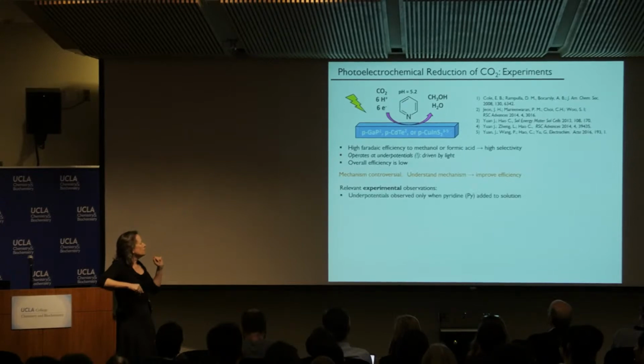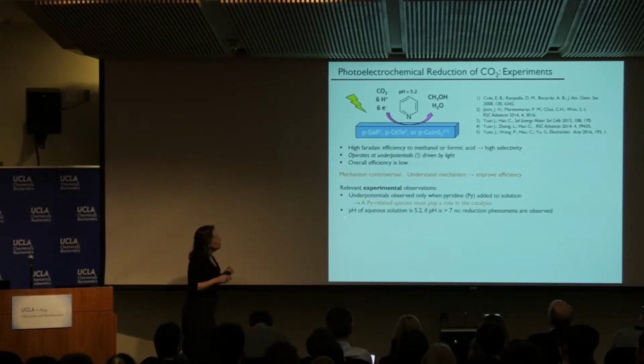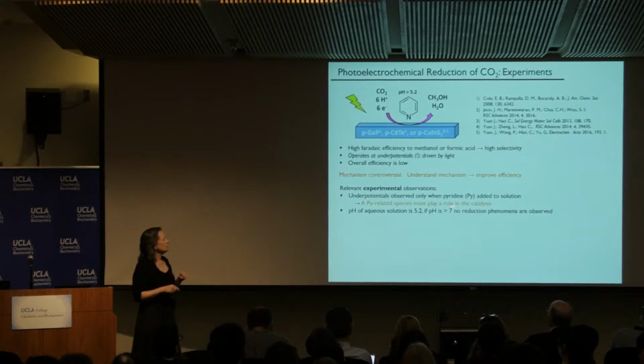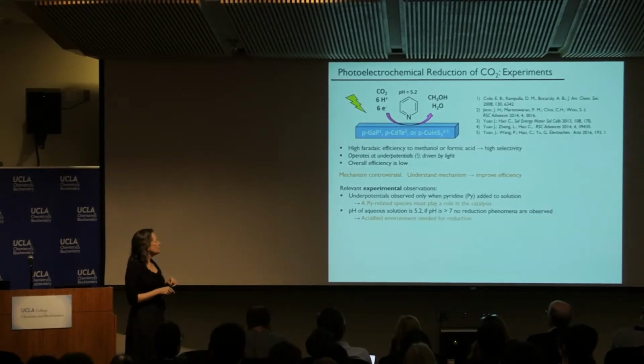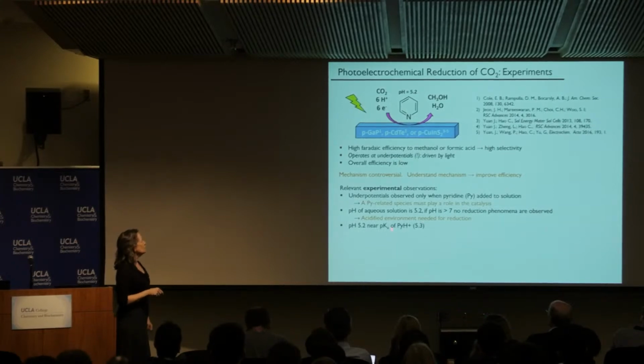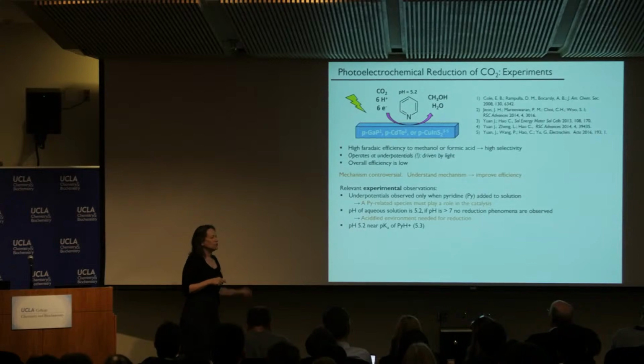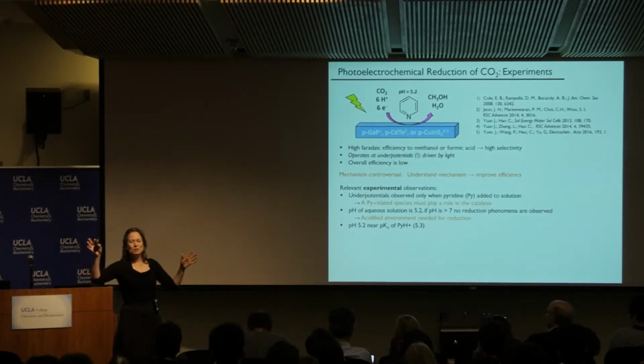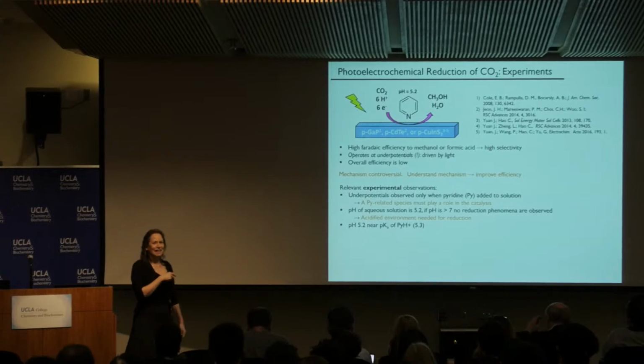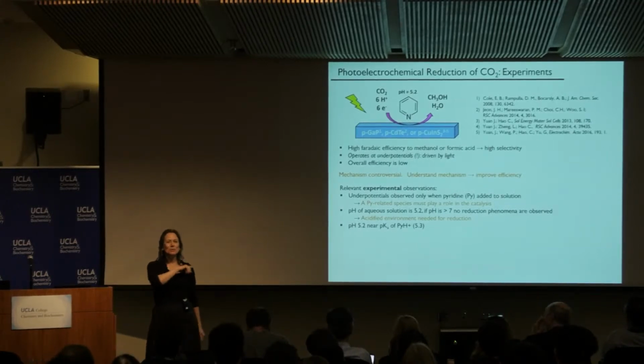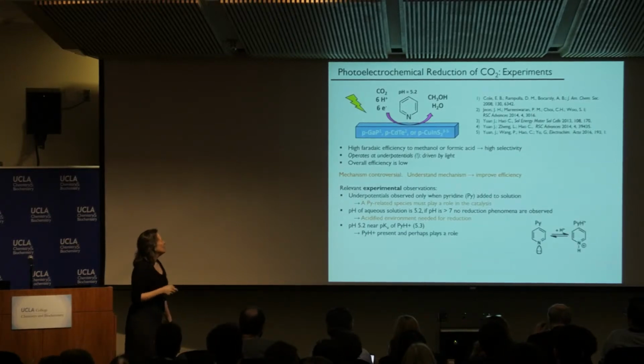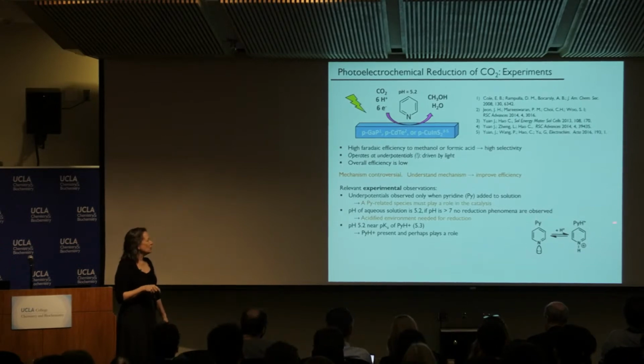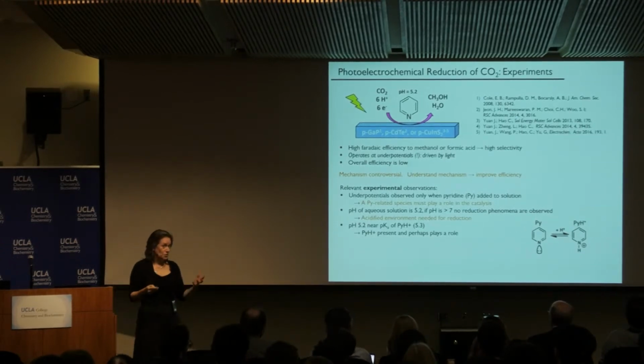Anyway, relevant experimental observations. Underpotentials only observed when pyridine is added. I told you that. So a pyridine-related species must play a role. If the preferred pH is 5.2, if the pH is greater than 7, you don't see anything useful happening. And that just means that you need protons around. Not surprising, because you need protons and electrons to do the reduction anyway. The interesting thing is that the pH of 5.2 that is optimal in this situation is very close to the pKa of pyridinium. So most of the people in this audience, I assume, are chemists. And so, in fact, that should immediately clue you in, if you've taught freshman chemistry, that you're dealing with almost a buffer solution, right? pH equals pKa. So what that means is that you have nearly the same concentration of pyridinium as pyridine in solution. So pyridinium may be playing a role, so you have to think about that.